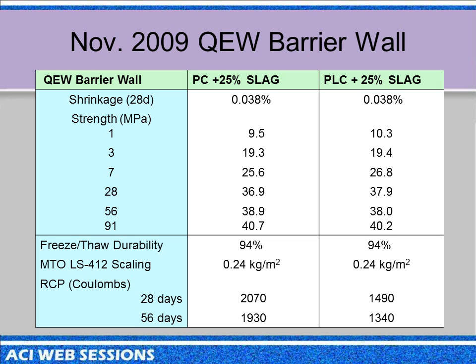These are the data, and I apologize, they're only in MPa here. But the shrinkage, drying shrinkage, was identical. The strengths, even 1 day strengths with the Portland limestone cement and slag, were better marginally. I mean, 0.8 of an MPa, you're looking at 100 psi. So I wouldn't say that's significant. But anyway, there's certainly no reduction in the early age strengths. Freeze thaw durability, C666, is identical. This de-icer salt scaling test is the Highway Department's version of C672, the ASTM test, except that you measure the mass loss. It's identical. And again, the chloride permeabilities are even better with the limestone cement at 28 and 56 days than they were with the straight cement.